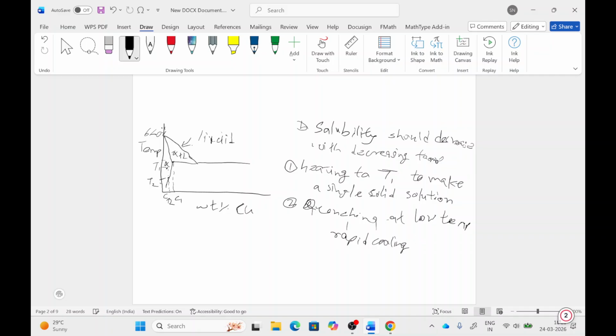In slow cooling, the copper will segregate from the aluminum matrix, but when we are doing quenching, there is rapid cooling, which helps in keeping the copper atoms in the aluminum matrix. So that solid solution is called a supersaturated solid solution.